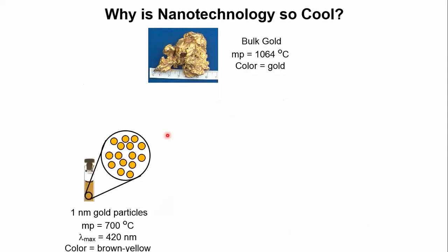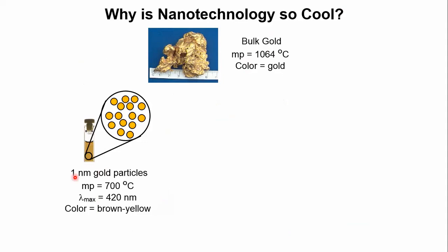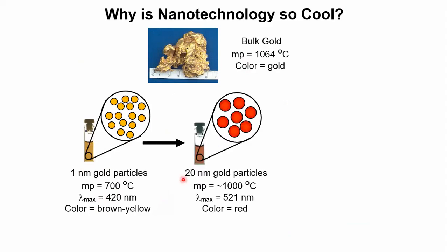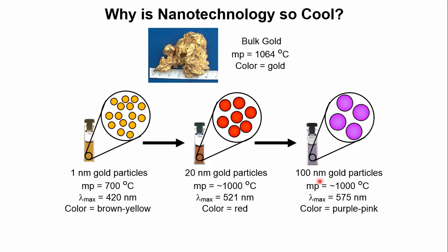So why is it cool? If you see the bulk gold, the melting point is 1064, but when you decrease the size, around 1 nanometer, it is 700 degrees centigrade, and the color is a brown yellow, giving a lambda max of around 420 nanometers. But when you increase the size to 20 nanometers, its melting point is around 1000, and the color becomes red. Then making it 100 nanometers, the gold particles have a purple, pink color. So we saw the optical properties changing here, and at the same time the melting point is changing. In bulk size it is 1064, but at 1 nanometer it comes down to 700, and if you increase again, it goes to the other side, 1000 degrees centigrade.